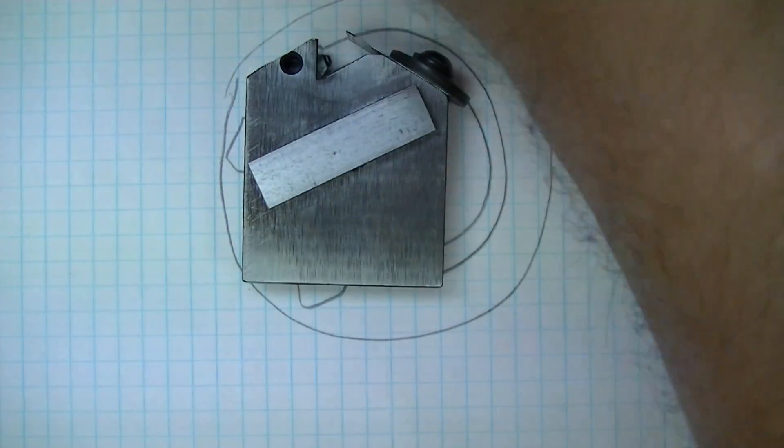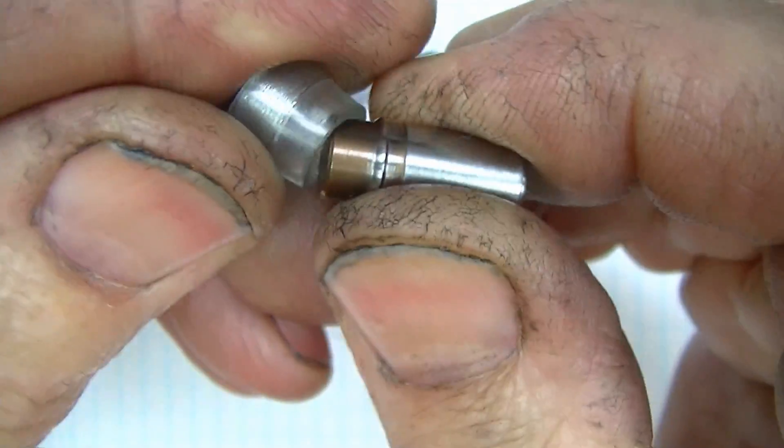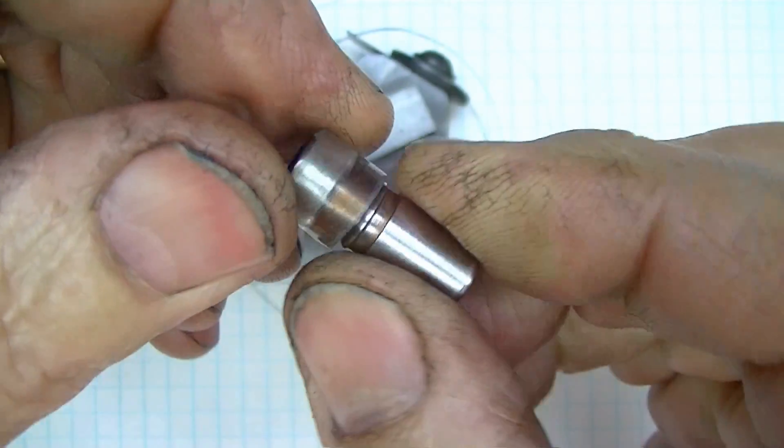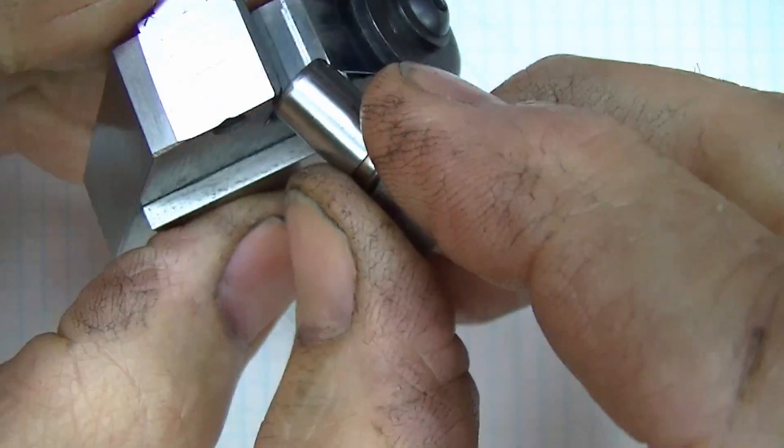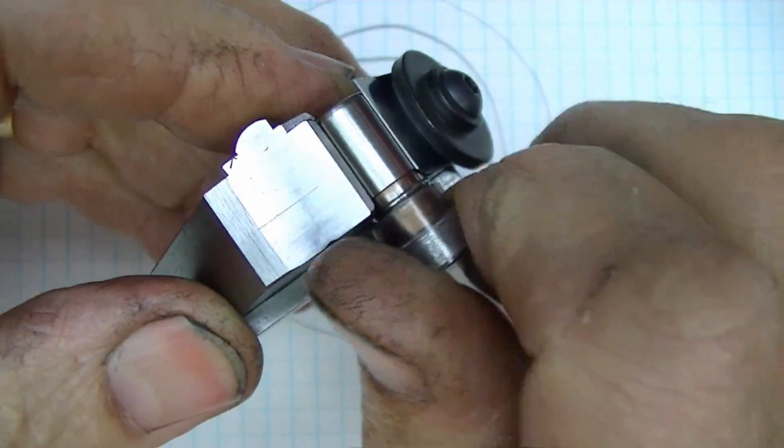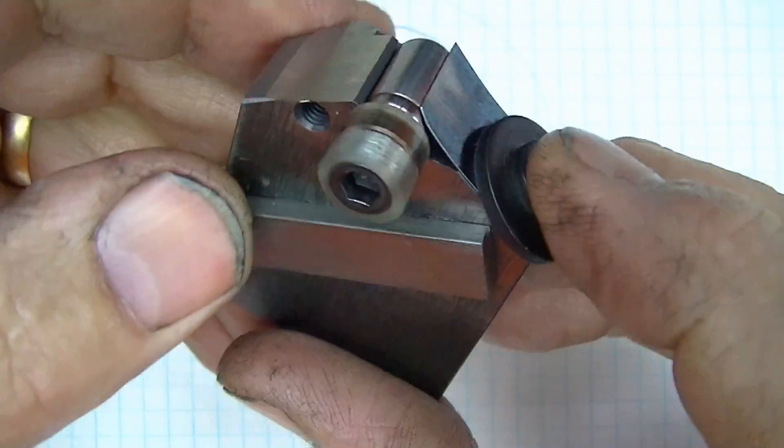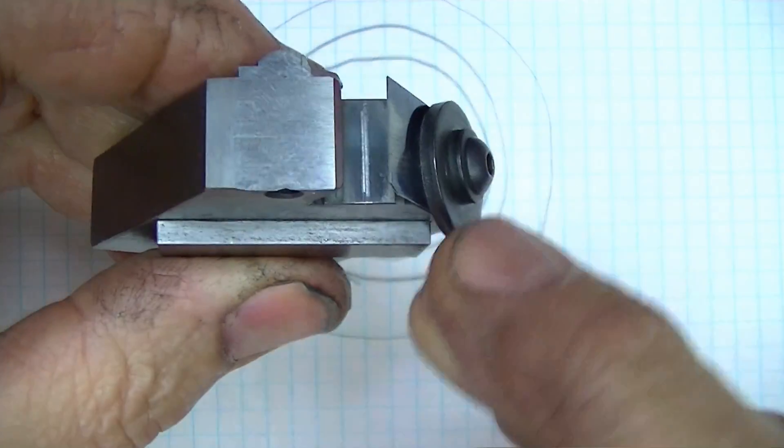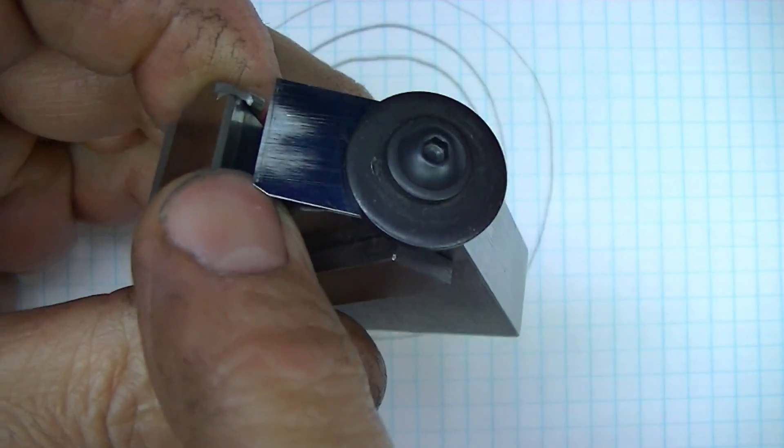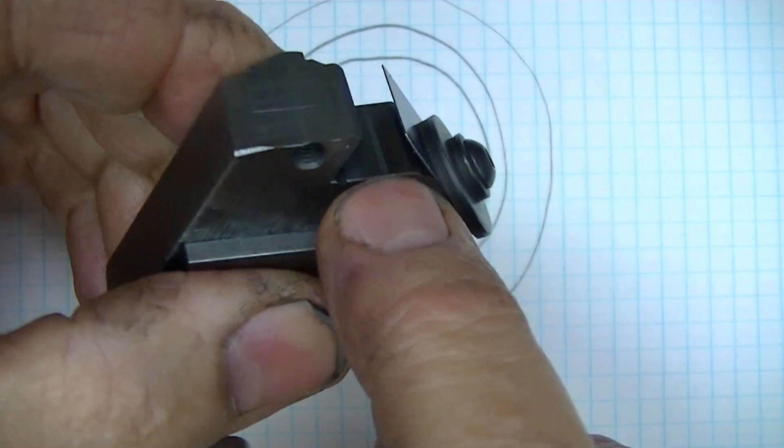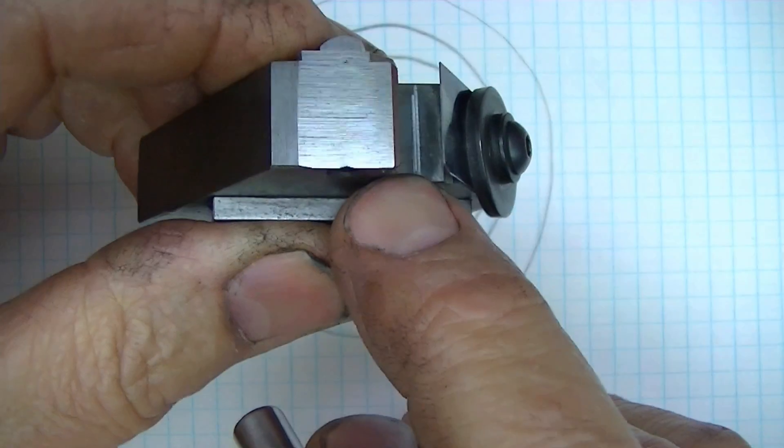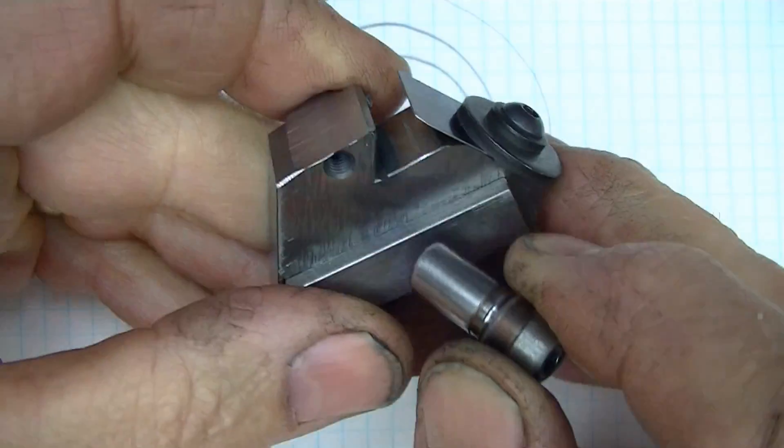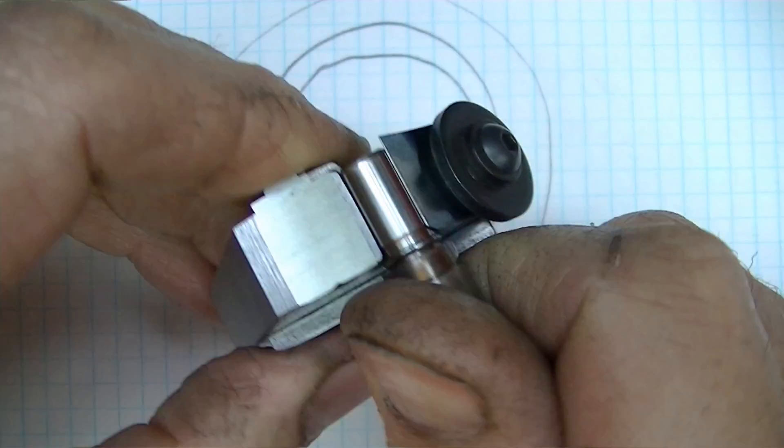You can see what's going on here now. I did these first and I wasn't even sure really how I was going to do the other ones. The other ones, I said yeah you know what I could probably take a piece of tubing like this and turn down the head of the screw so that it's also a press fit in the tubing and then put these in. That's exactly what I did, same drill arrangement, and spun them like this. When I ground the flats here I actually put them in the vise, the same vise that I used to hold it. So I ground this and then I ground this bearing face back here. Remember this is hardened A2 here. I actually just sort of induction hardened these with a TIG torch in the areas where I needed it to be hard, the rest of it's still soft. That way when I put this in the vise I was really getting good straightness.